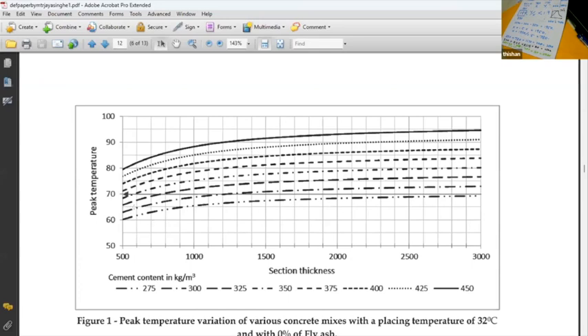But the moment you go up to 300 cement, what happens? Temperature exceeds 70, so anything beyond 1.2, 1.5 meters is in danger of cracking, forming DEF. So how can we prevent this situation? Okay, so what we do is, we use 275 cement, but we would like to have about 350 cement. So what are we going to do with the remaining cement? Instead of using cement, we use fly ash.